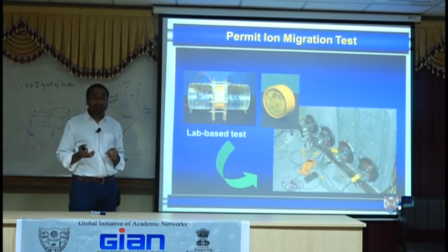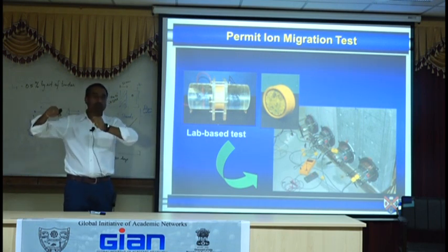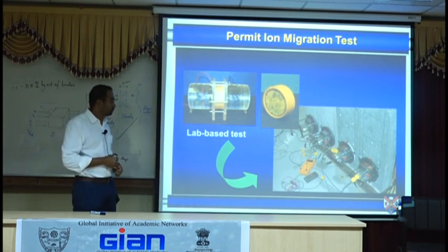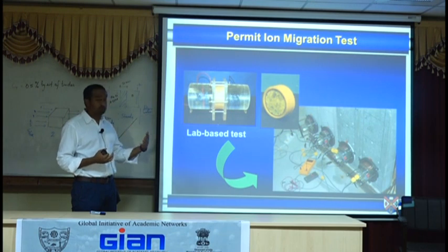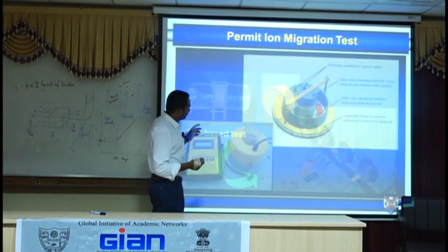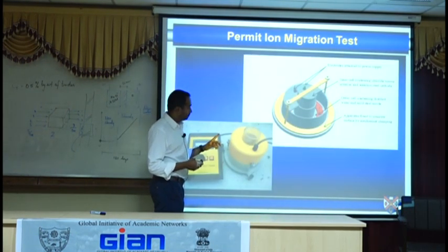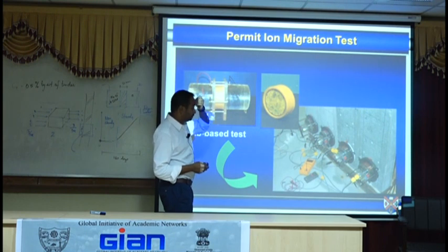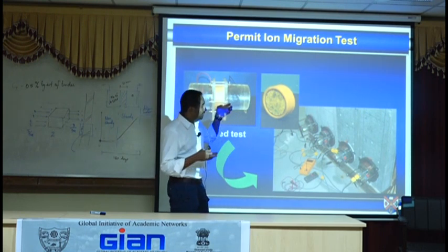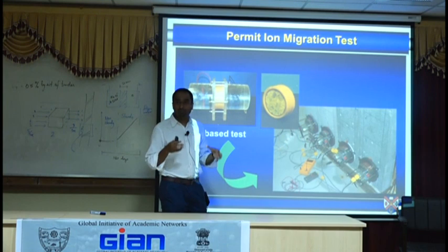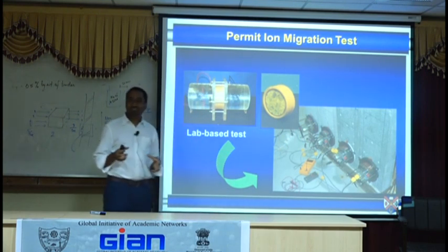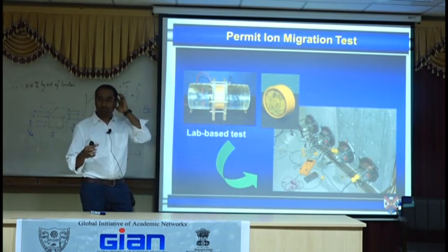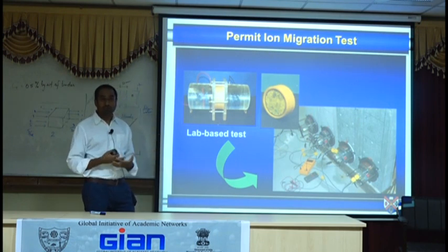And thirdly, depending on access, it may not be that easy to take cores. A core drill is quite a heavy machine. You're going to have anchor points to core it to. So we were looking at tests that can be applied on the surface and do the job. So we then came up with this test, which is a prototype is what you're seeing there.